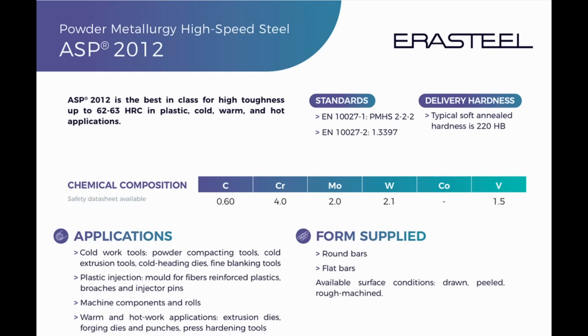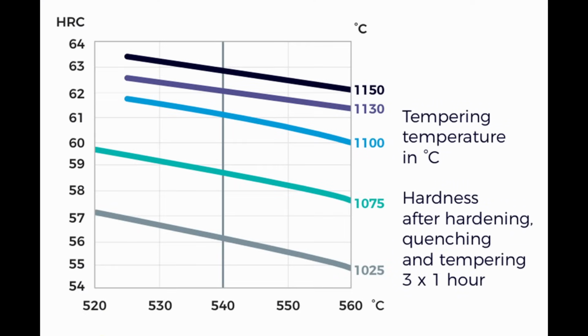Now, there are some other steels out there I haven't tested. One is ASP 2012 from Erasteel. It also is a low carbide volume steel, but its data sheet shows it getting to 63.5 Rockwell or so, it gets no harder than the CPM1V. So maybe it has a bit better properties. We wouldn't know until we test it, but it's not in a completely different realm of properties. It would be roughly similar.